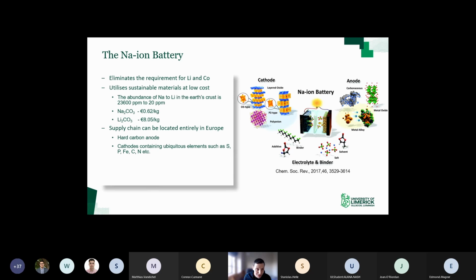They're also less costly. Sodium salt, or sodium carbonate, is less than a tenth of the price per kg of lithium carbonate. And the supply chains can be located entirely in Europe. If you're looking at a hard carbon anode, or the elements in the cathode, which are much more ubiquitous, like sulfur, phosphorus, iron, and so on, in the long term there's no real risk to the supply chains for sodium-ion batteries, which is another advantageous property. Another good thing is that you can leverage the decades of research that's gone into lithium-ion, because the chemistries are similar. They're not exactly the same, obviously, but they're very similar.